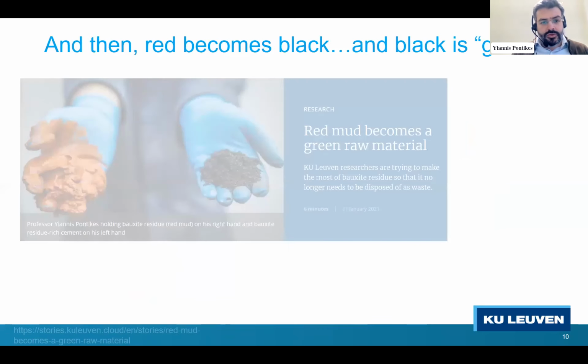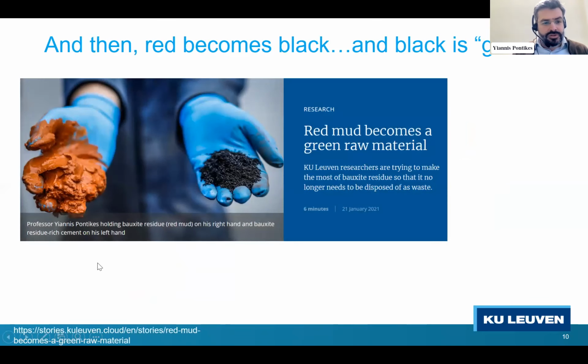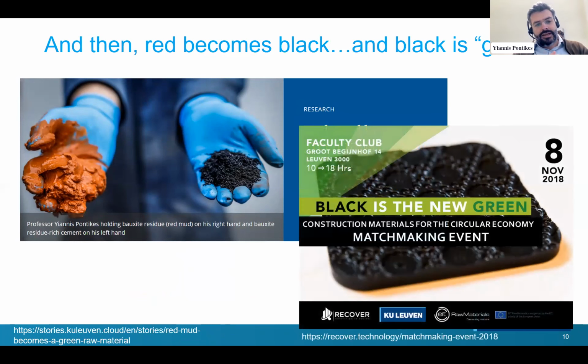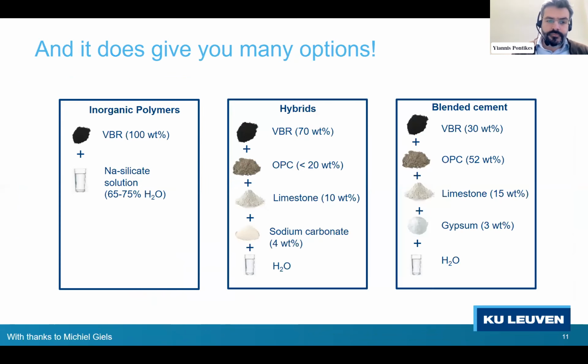What do you do afterwards? Yes, some publicity first to conceptualize the thing. Your mud becomes a black slag. And then you bring together, and I think that's the interesting thing, all the non-ferrous metallurgy, both the alumina refineries and the copper and the lead slags, to create this black precursor. And you can play with the words: the red becomes black and the black becomes green.